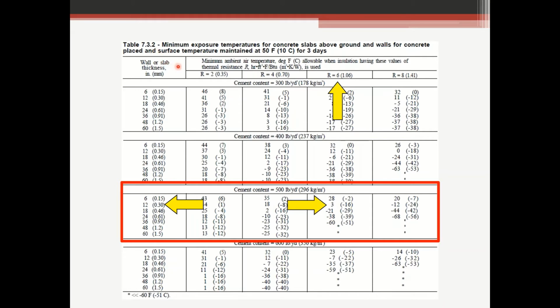So what this particular table is telling us is what R value we need for different ambient air temperatures. And this is assuming that everything was placed at 50 degrees, that's table 5.1, placed at 50 degrees. And assuming all these conditions are met, in theory, it should maintain that 50 degree temperature for 3 days if we're doing all of this. So this column here on the left side is the wall or slab thickness. We've got 6, 12, 18, 24, so various thicknesses. Each one of these sections is for a different cement content. This section right here is for 300 pounds per cubic yard. This is for 400 pounds per cubic yard. The one I've got highlighted here is about 500 pounds per cubic yard. The mixes we see these days are typically 500-600 pounds of cement per cubic yard for 3,000, 4,000 psi concrete.